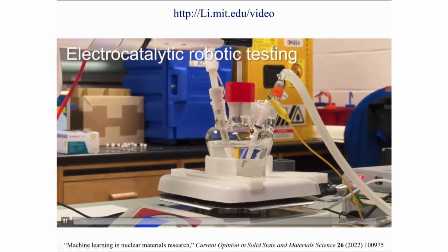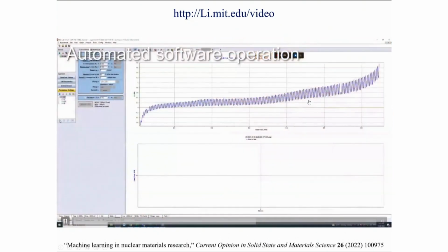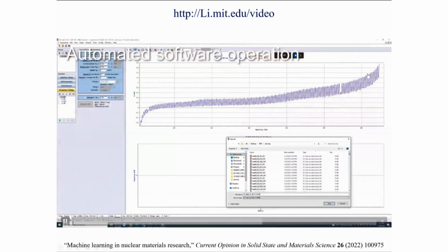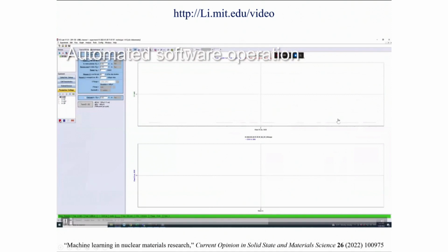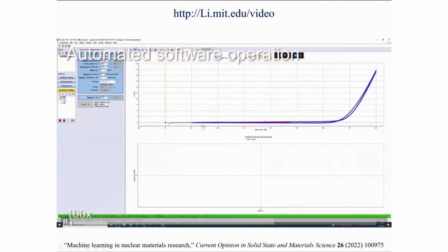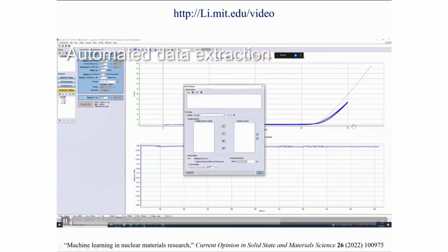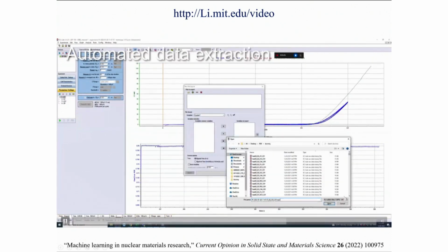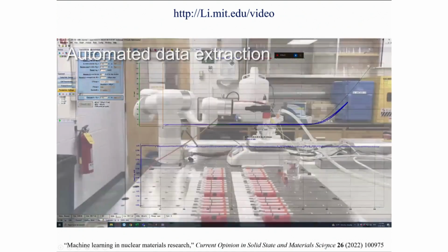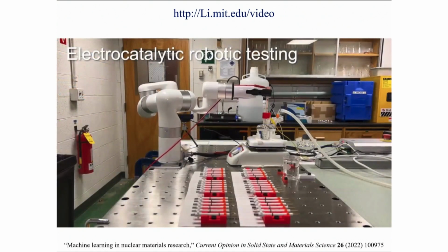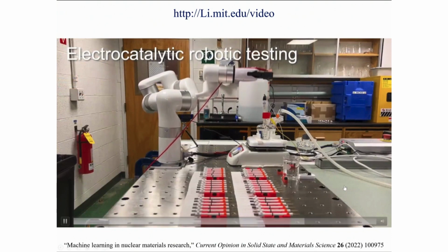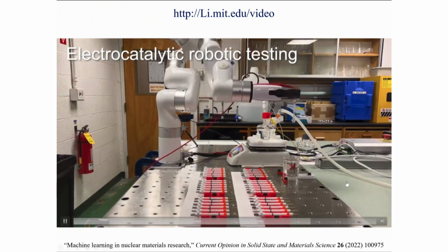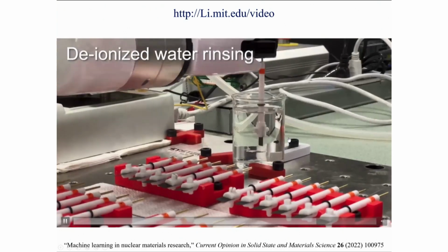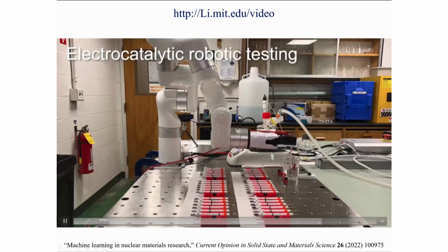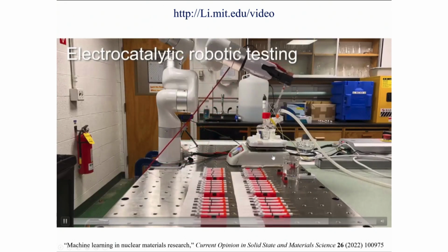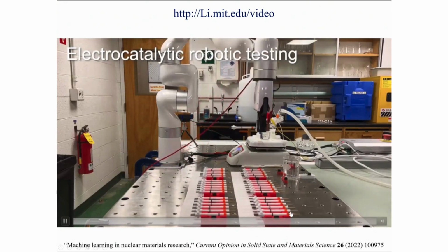So here we're running the oxygen evolution reaction, which is used in the water splitting electrolyzer to produce hydrogen in an alkaline solution. And what you see here is the automated linear sweep voltammetry, and it looks like somebody is typing, but it's really a script. And then we're able to change samples. So overnight, we can do 10, 20 such experiments. So we rinse it because it's in KOH solution, and then swap on the next experiment.